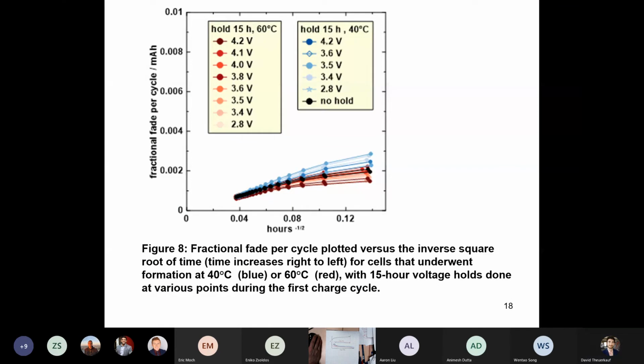Yep, it's true. Okay, so here we're plotting the fractional fade per cycle. So this is equivalent to the growth rate of the SEI. How much did the SEI grow per cycle? The amount of capacity that you lose per cycle, that lithium ends up in the SEI. So a plot of this versus time to the minus a half should be a straight line.